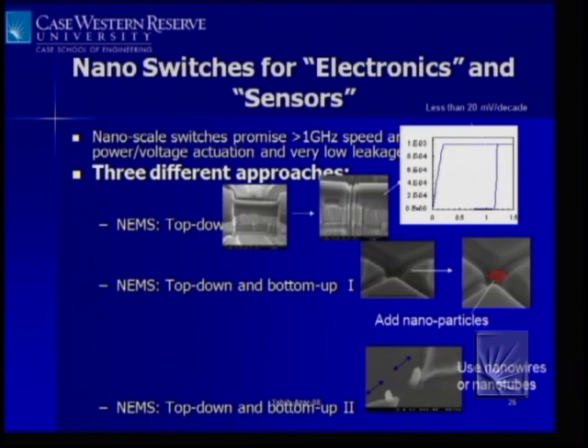So we created these carbon nanotube-based switches and discovered that the capacitance between them is exceedingly small. That's good in some applications, but for switching applications it's not good, because you want the voltage for the switch to be compatible with CMOS. That sets you around 1 to 2 volts. The capacitances between these two are so small that you need like 10, 15 volts to switch them. Once you apply 10, 15 volts across these carbon nanotubes, as soon as they switch, they burn. So not a very good switch.